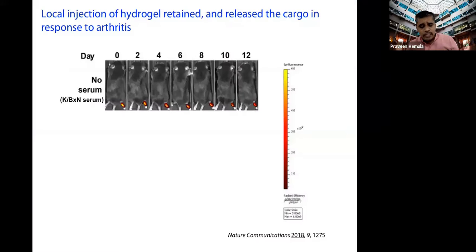Then after that, we wanted to see, if you don't have inflammation, whether the gel that is injected into the joints can remain there without releasing the drug. And whenever inflammation comes, will it be able to release the drug? To test that, we took healthy animals which don't have any disease, fluorescently labeled these gels and injected them into the joint. Over a period of a couple of weeks, you don't see much reduction in the signal, and this signal is localized in the joints, which is clearly suggesting that if there is no inflammation, the gels are still there and they're not releasing the drug, right? And despite the mechanical stress, because these animals keep running and walking around, you don't see depletion of signal.